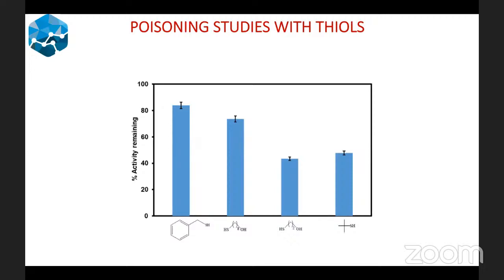So we chose these thiols to do these poisoning studies reactions. And of course, you should expect bulky thiols not to move into the pores of the MOF because of steric hindrance. Probably their size is much bigger than the pore size. So if they are not able to move into the MOF, it means they are not able to poison the catalyst. These thiols have been known to poison catalysts. By poisoning, it means they will reduce the catalytic activity.